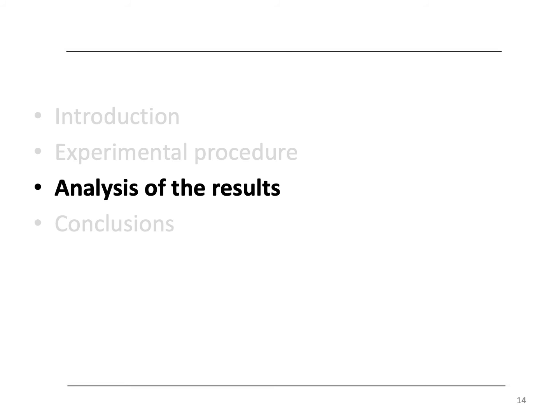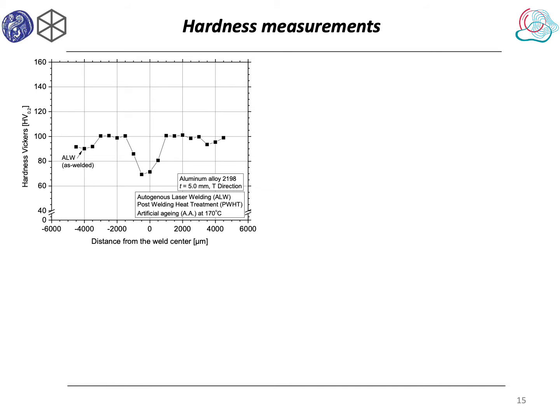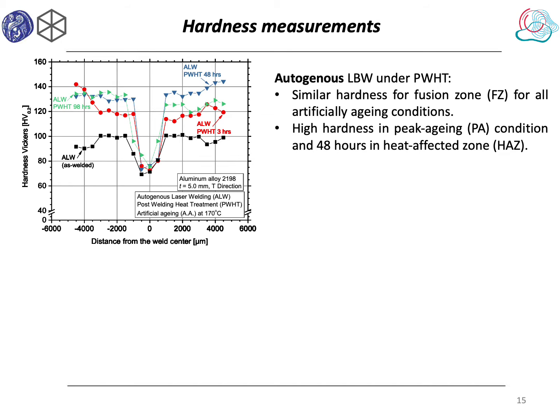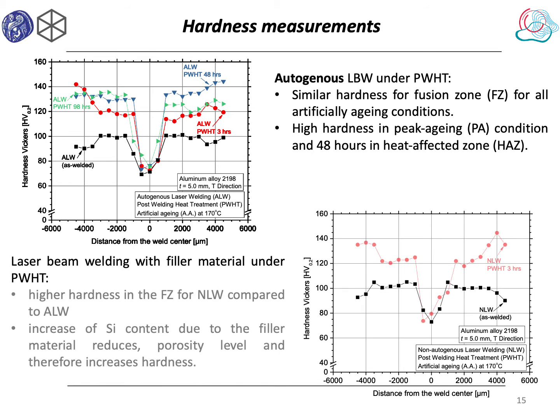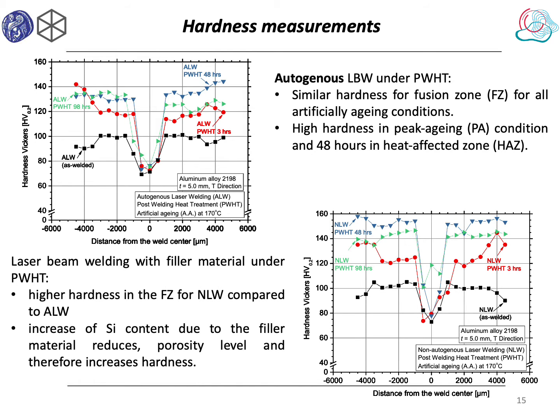Continuing with the analysis of the results, here we can see Vickers hardness versus distance from the weld center for autogenous welds under different artificial aging conditions post weld. With increasing aging time, the fusion zone presents similar hardness for all conditions. Higher hardness can be noticed for the peak aging condition at 48 hours. Non-autogenous laser beam welds with increasing artificial aging times present higher hardness compared with autogenous welds, which can be attributed to the addition of the filler wire and the increase of silicon content.